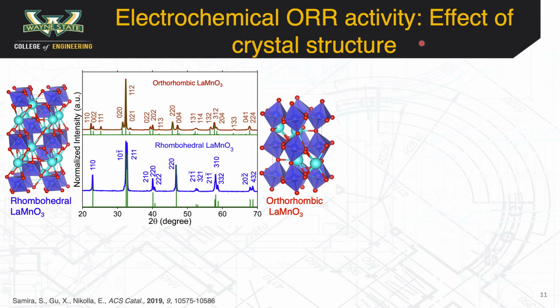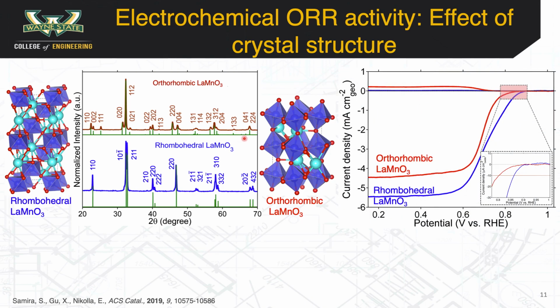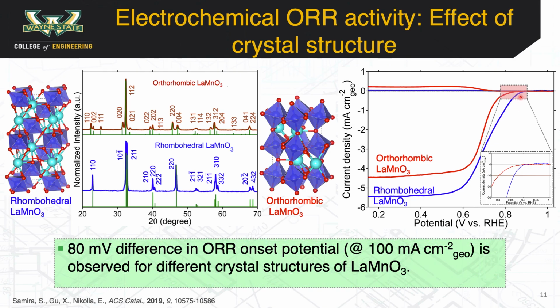Initially, we start off by studying the effect of crystal structure on the electrocatalytic activity. One of the good things about LaMnO3 is the fact that it can be synthesized in two different crystal symmetries based on the calcination conditions. We then move on to study the electrocatalytic activity towards ORR and find that there is an 80 millivolt difference in the onset potential between the orthorhombic and the rhombohedral crystal structure, suggesting that the crystal structure plays a crucial role in determining the electrocatalytic activity.